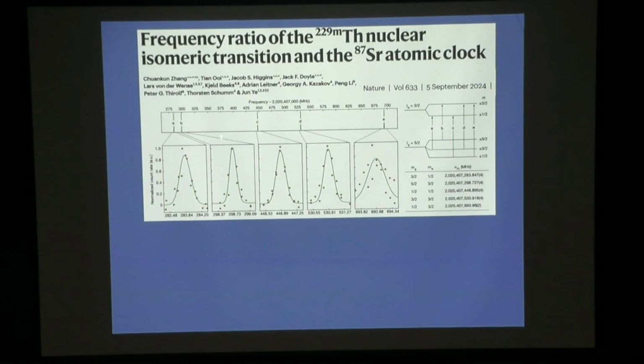And what he saw was the individual states. So the ground state is I equals 5 halves, the excited state is nuclear spin 3 halves. The crystal has an electric field gradient, and the nucleus has a quadrupole, so the levels are split by the quadrupole, so they split by the absolute value of M. And you expect 5 transitions. Actually, 6 is allowed by mixing, but they observed 5 of them. And the line width that they see is a few hundred kilohertz, and from their experiments, that's their laser. That's not actually the transition yet. So we don't actually know what the line width is yet. And everybody is working on narrowing their line widths to address this.